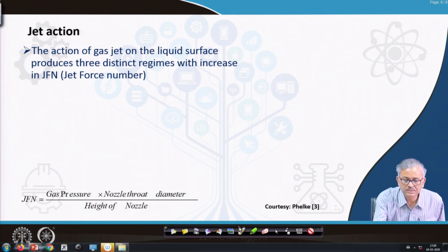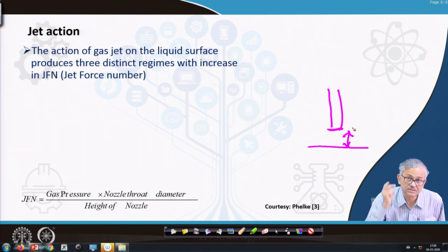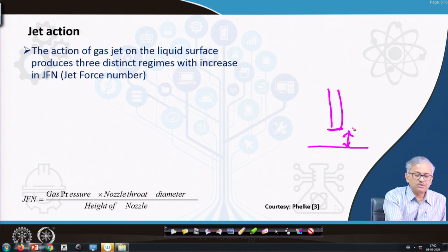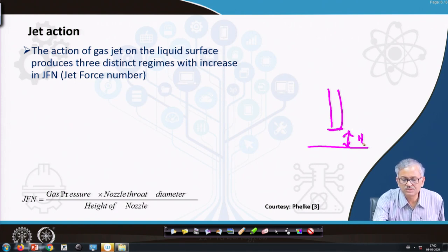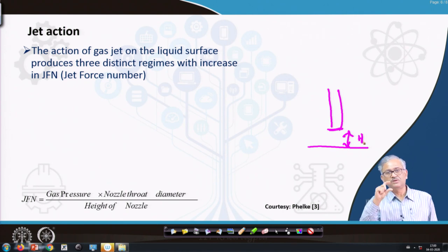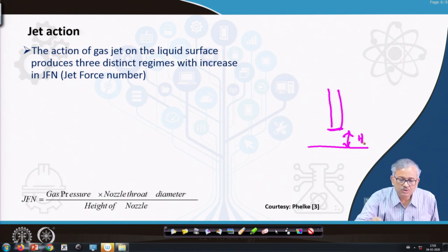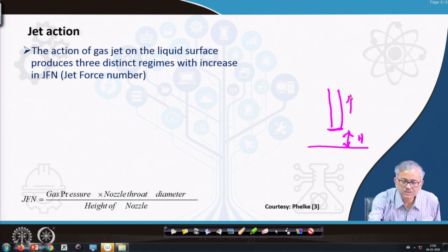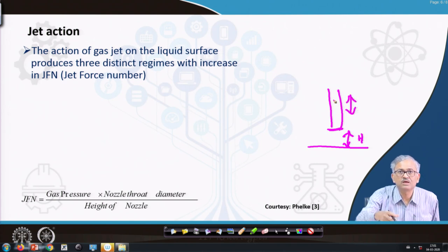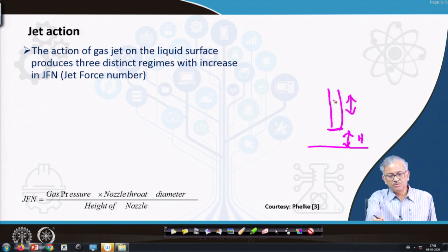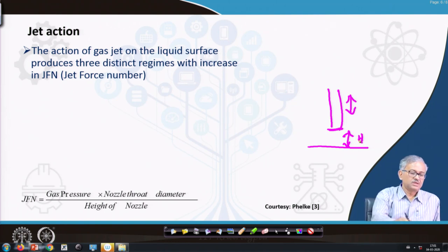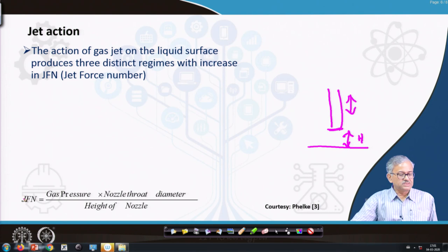So if you have a bath here, this is the bath, and this is the oxygen lance. This distance is called the height of the nozzle, which you can control. You can take the nozzle up and down and change the value of H. And you can control the JFN.